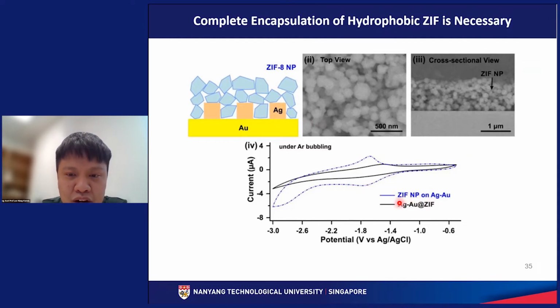Yeah. So in our thin film configuration, we can exclude the excess water efficiently, and there is no presence of water electrolysis peak around negative 1.8 volt and negative 2.8 volt. However, when we deposit these nanoparticles onto our bimetallic catalyst, we can still see the presence of water electrolysis peak at negative 1.8 and negative 2.8 volt. So this again tells us that complete encapsulation of hydrophobic ZIF across the entire bimetallic catalyst is necessary.